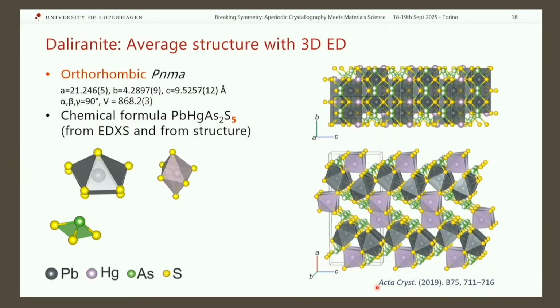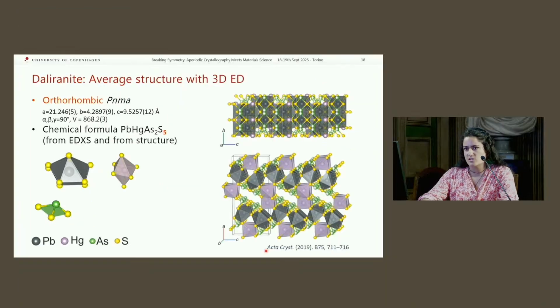So here we could easily find the unit cell from the dimensional data. Actually, the unit cell is different. When you look at the whole data, you get the correct one. And also, the formula turns out to be a bit different from what was initially determined from the structure, and then again confirmed from locally energy dispersive X-ray spectroscopy, we can see that the formula actually contains only 5 sulfur, not 6. So this is also the importance of being able to perform the chemical analysis exactly on the crystal that you are diffracting, so you can correlate best.